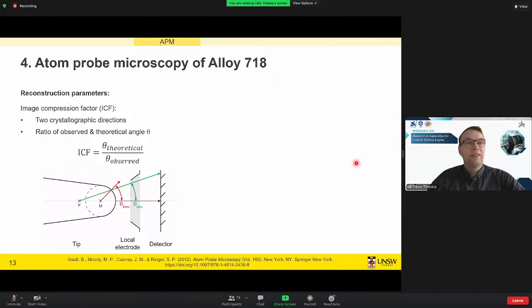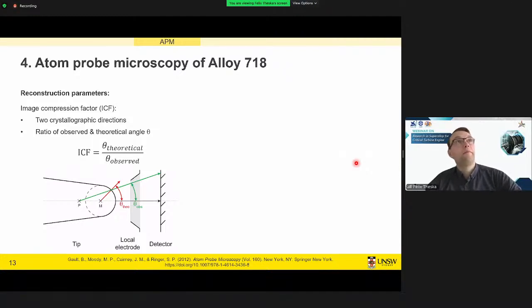Okay. Now I said we get the X, Y, and Z coordinates, but the coordinates we record are not necessarily the actual coordinates. So there's a fair bit of reconstruction necessary to get to the true coordinates, or as close as possible. The two main reconstruction parameters are, on one hand, the image compression factor. For example, if we know features in our data set and their location, such as some crystallographic information, and they do not overlay with the actually observed location, we can correct this. And that's just done by this rather simple ratio.